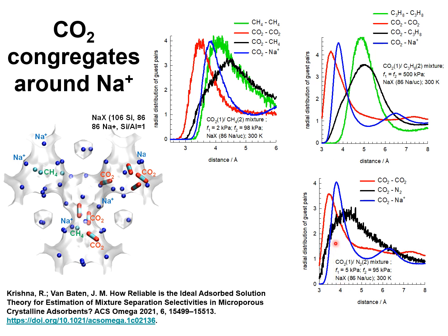The same holds for CO2 and nitrogen. The distance between CO2 and nitrogen is typically larger than the distance between CO2 and the extra framework cation sodium.